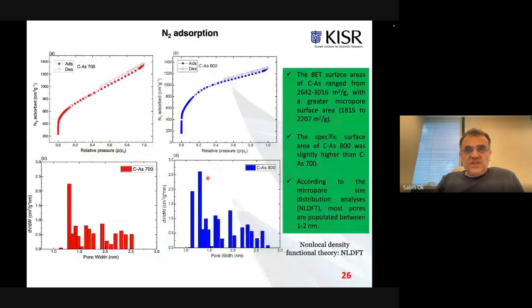Of course, again, we focused on surface area measurements, and we recognized that the BET surface areas of those carbonized asphaltenes range from 2,600 up to 3,000, which is a very nice result for us. And again, as in the case of cross-linked asphaltenes, we're able to observe pores down to 1 to 2 nanometer by the NL-DFT approach.